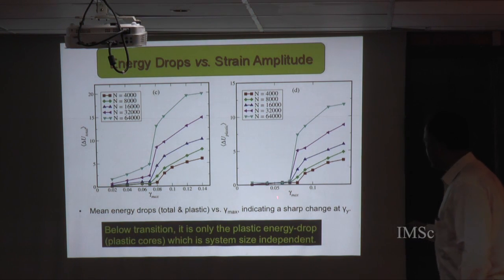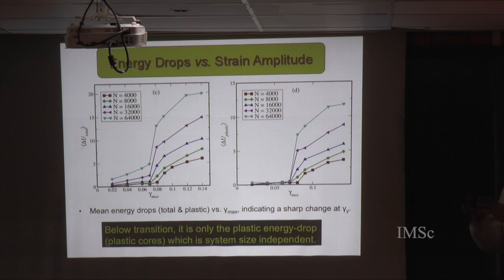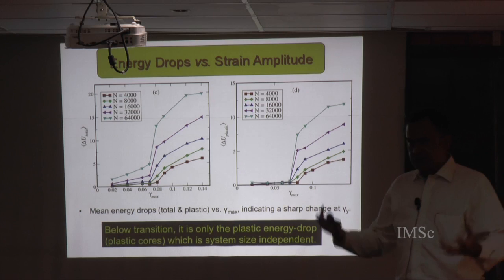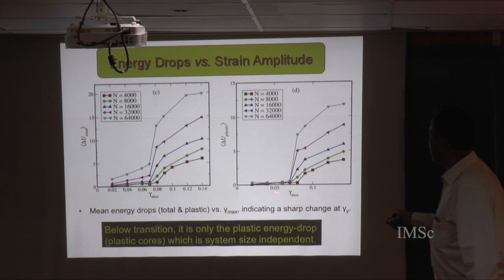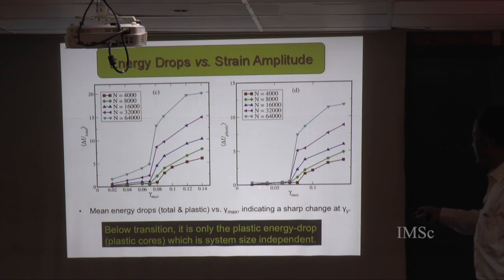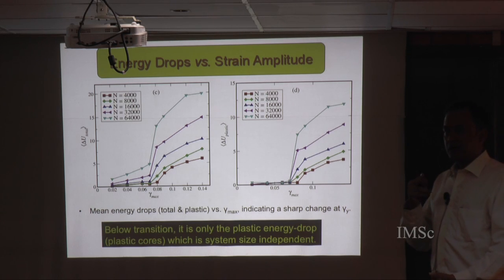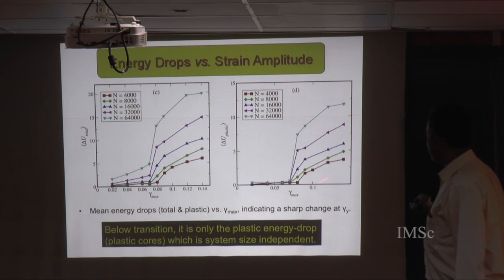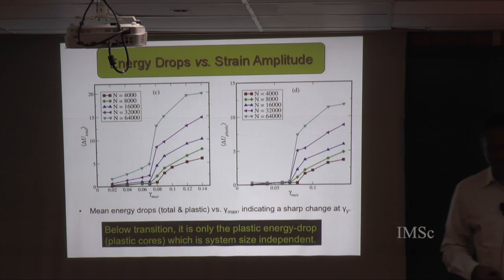Okay, and so if you sort of don't take care, you'll find size effects also below the yielding transition. But if you take care of that by focusing on energy changes only for the particles you identify as the plastic core, then you have the same picture of there being no size effect, no large energy drops below the yielding transition, and size effects and large energy drops above.